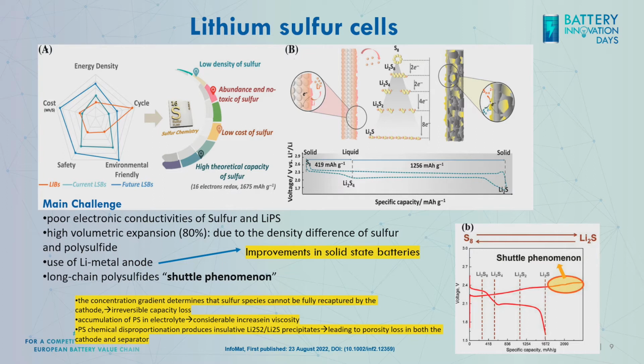So let me show you, this is a very dense slide, but let's start from the above figure that is coming from a publication of 1 month ago. That is very nice, summarizing the lithium-sulfur cell. Lithium-sulfur is a very simple system somehow, because it's composed of a metal lithium as an anode, and a composite of sulfur and carbon as the cathode. And in between, there will be a liquid electrolyte. On the left-hand side here, you can immediately compare the performance of a lithium-ion cell in orange with the actual and the expected one for lithium-sulfur, and you can see immediately that the energy density is huge.